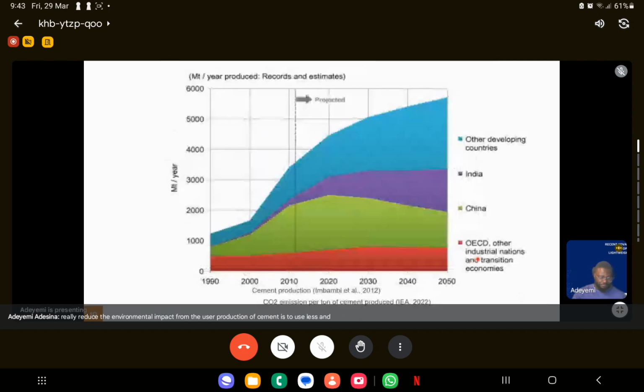So, as we all know, the main reason is first, the calcination process. During the calcination of all these raw materials in the kiln, one of the products is carbon dioxide. Even though there's a lot of research and development recently trying to use alternative fuels for the production of cement, even if you're able to reduce this emission to about, let's say, 50, 80 kilograms per ton, there's still a lot of this coming out. Which means one of the ways we can really reduce the environmental impact from the use and production of cement is to use less and find alternatives.